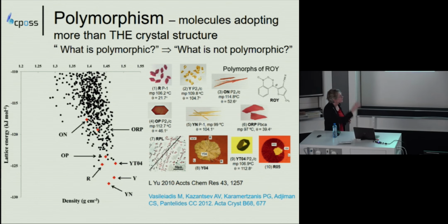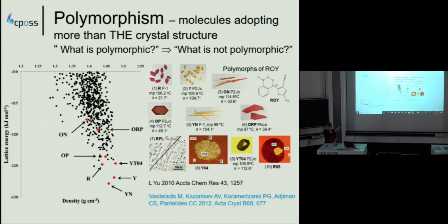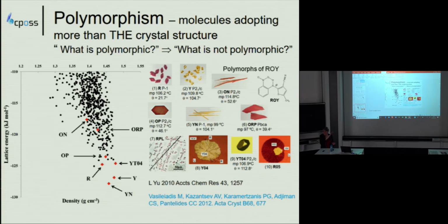Okay, so there you've got the examples of the different morphologies as a function of polymorph. And yes, there is quite a lot of work being done on trying to develop methods of predicting morphologies. We do, in our database, occasionally do a very simple method that is solvent independent, based on the attachment energy methodology, mainly to look at whether you are expecting an extreme plate or needle, and look at relative growth rates. And one of the advances that is happening is that more and more crystal structures are based on needles or plates.